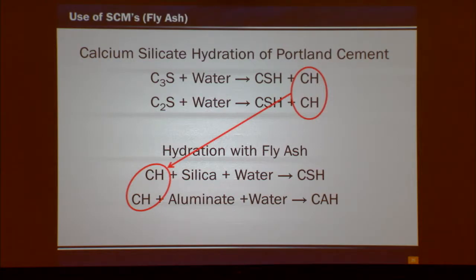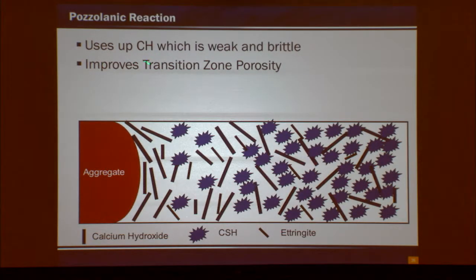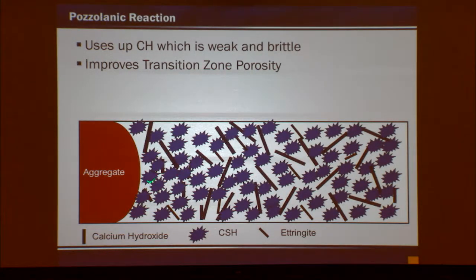So where does the porosity thing come into play? All right, so let's look what happens when you use fly ash. Again, we use up that calcium hydroxide, and then we have this phenomenon of improving this transition zone, right? So if you look at an aggregate, that calcium hydroxide that is produced, it's plates. I don't know if you saw some of those presentations early on show those micrographs. So calcium hydroxide are these flat plates, and they line up along the aggregate. So this zone right here is very porous. So water comes in and it's going to find those zones and just trickle its way down through the concrete. So again, when we use fly ash, we use up this calcium hydroxide and we make more glue. So there we go. We have now improved the porosity of that region, and now that is more like the bulk paste out in the middle.